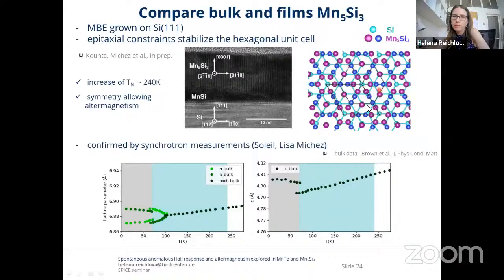However, we also confirmed that by synchrotron measurements. What I show here is the temperature dependence of the lattice parameters of the bulk Mn5Si3, as reported by Brown. And here is the c lattice parameter. This is showing the transition at the second Néel temperature. Here is the ab lattice parameter. So the bulk films are hexagonal in the paramagnetic phase. Then the first transition is from the hexagonal to the orthorhombic, and then the low temperature phase is monoclinic. And all these transitions can be seen in the a and b lattice parameters of the bulk measurements.